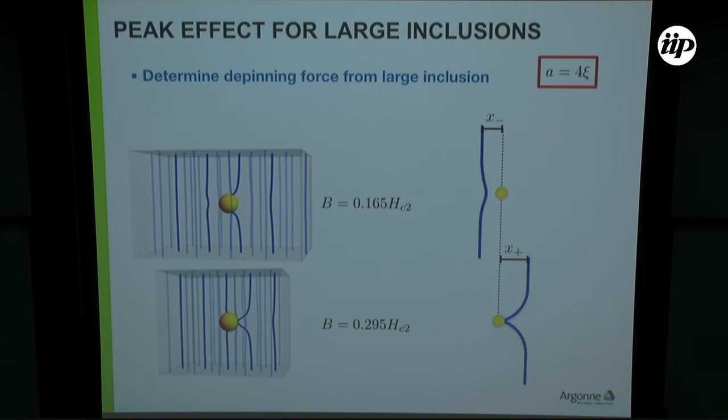So here, again, are the pictures of the critical states. We see that as a function of increasing field, we have 2 very different pictures. Here in the critical state, we see that 1 vortex is sitting in the defect, and the vortex in the back, you already see that it's getting unstable because it starts to deform towards the defect. And the instability in the critical state is that of the second vortex becoming unstable and kicking out the first vortex. In this case, the critical state consists of 2 vortices sitting in the defect, and then the first vortex decides to leave the defect.